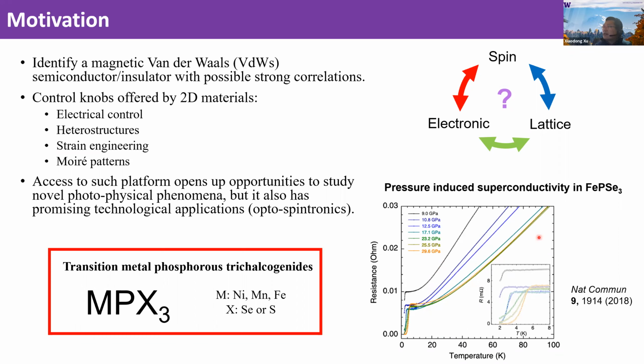It is itself a zigzag antiferromagnet, but under hydrostatic pressure, there's a phase transition from this magnetic order into a superconducting order. What you're seeing here are resistance measurements of these crystals as a function of temperature. At high pressures, there's a superconducting transition. You can see that the resistance drops to zero with a critical temperature on the order of 4 to 5 Kelvin. From this simple example, you can already see that the material system has strong correlation effects.